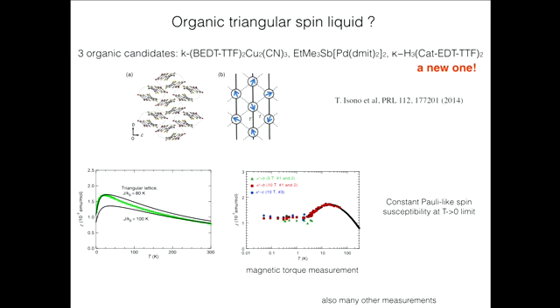So they did a very careful measurement. At high temperature, you get some Curie law. But at low temperature, the spin susceptibility deviates from the Curie law. And in fact, if you look closely, in the zero temperature limit, the spin susceptibility becomes a constant. So this is very much like a Pauli spin susceptibility in a liquid metal.